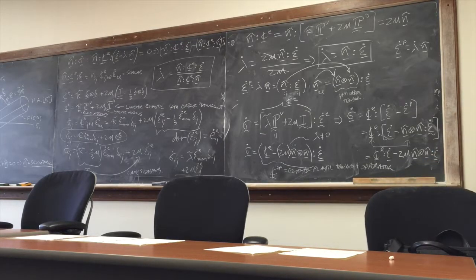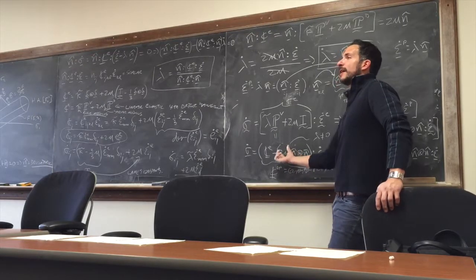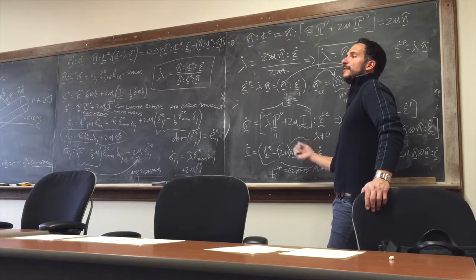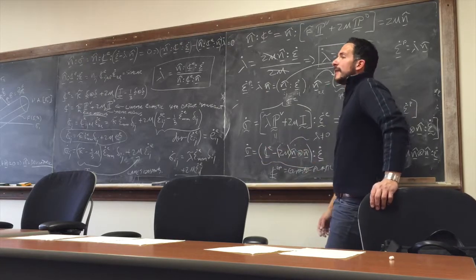Any questions? I think that it is important to point out that the CEP only works with plasticity. So I've seen a lot of people coding it from the beginning and computing the CEP from elasticity, and then they go like, Drucker-Prager doesn't converge for the first time. It's an exceptional case. I found it. Yeah. And the mistake is in computing the CEP. So that's why it's important to remember that this second part is only there. That's why the Macaulay brackets. So they're only present when lambda dot is not 0. If you're in an elastic step, this guy gets dropped out, and then everything is just given by the elastic part.